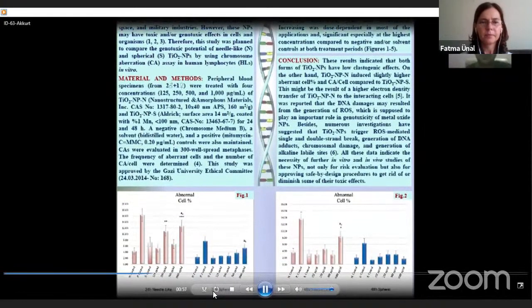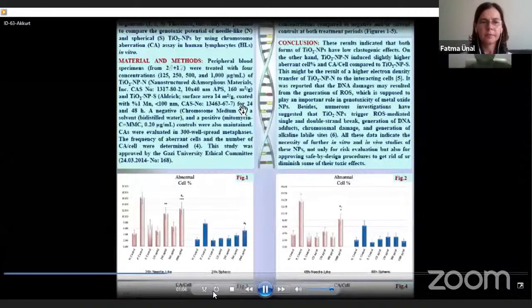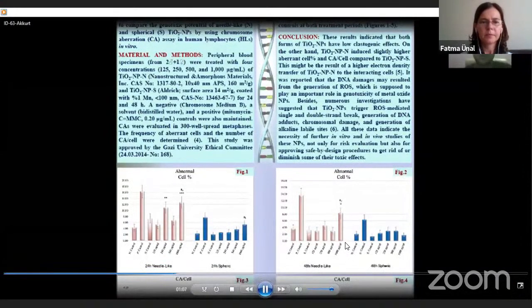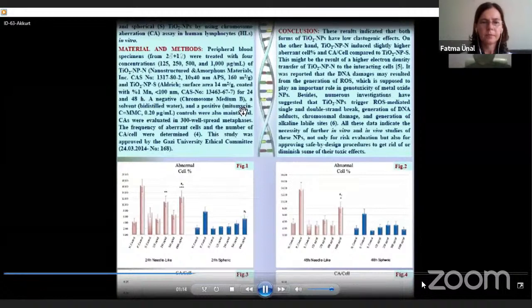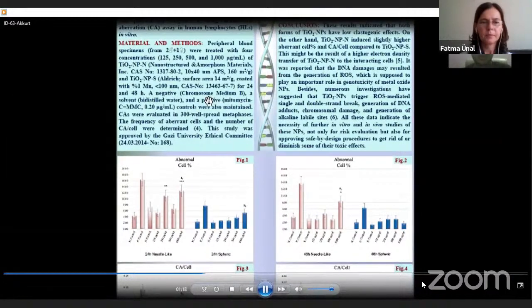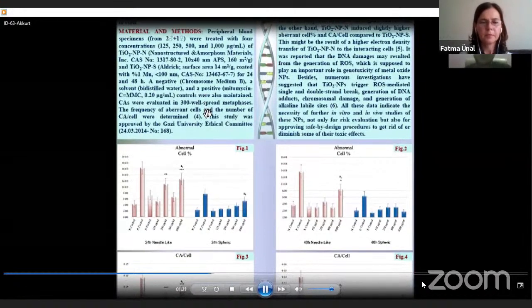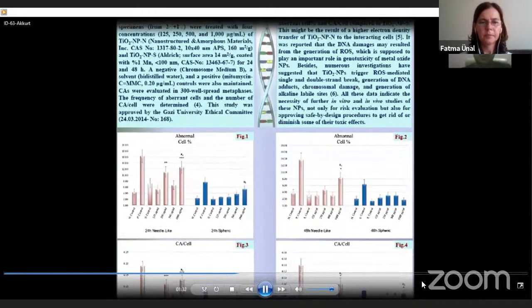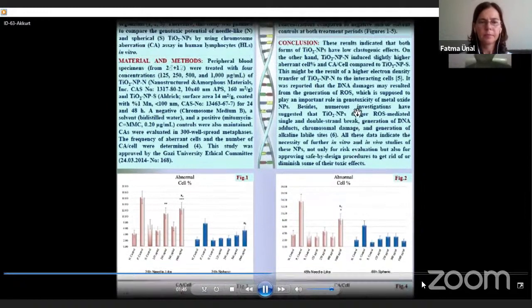In this study, we provided peripheral blood specimens from 2 male and 1 female donors, treated with 4 concentrations: 125, 250, 500, and 1000 micrograms/milliliter. We used titanium dioxide nanoparticles in needle-like form and spherical form, as you can see. We also used a negative control, which is chromosome medium B, a solvent control, which is distilled water, and a positive control, which is mitomycin C. Chromosome aberrations were evaluated in 300 well-spread metaphases, and the frequency of aberrant cells and the number of chromosome aberrations per cell were determined. This study was also approved by the Gazi University Ethical Committee.